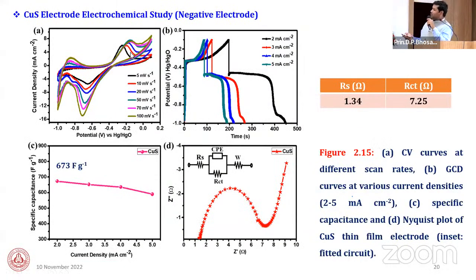Then I studied the electrochemical behavior of the single electrode only. It means this is a negative electrode for single electrode purpose. I tested CV and charge discharge electrochemical performance using different scan rates and different current densities, and the specific capacitance of this negative electrode is 673 farad per gram at a 2 milliampere per centimeter square current density.